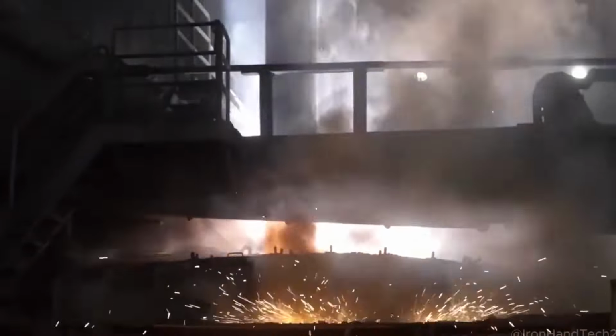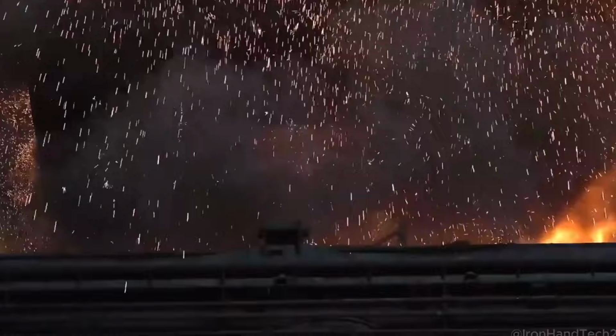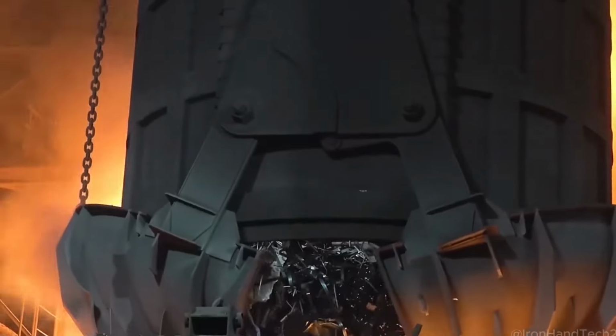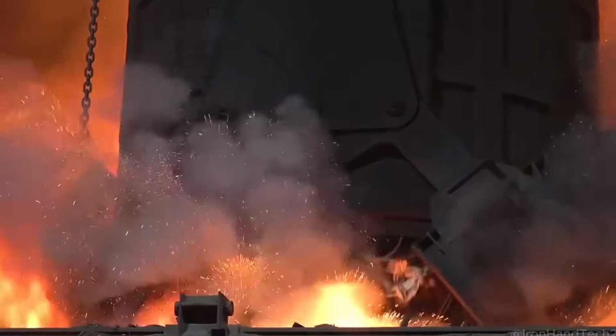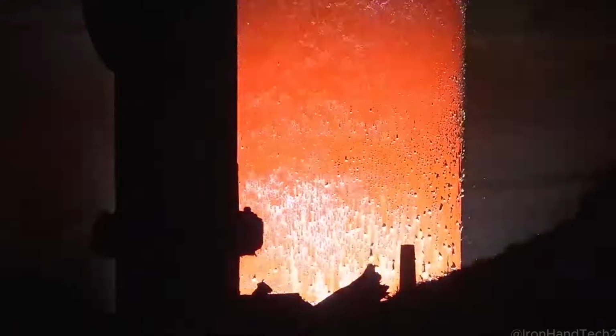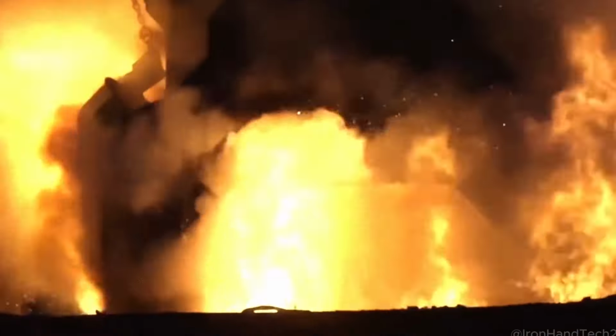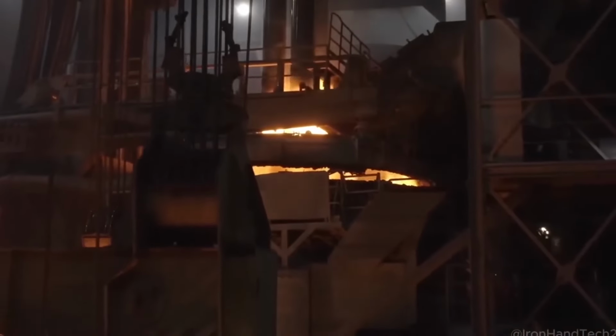This is where steel goes through its biggest transformation. Giant steel baskets, packed with shredded metal, are lifted high and tipped into electric arc furnaces, some of the hottest places on Earth. Unlike traditional blast furnaces, which burn iron ore and coal, electric arc furnaces run on electricity. This makes them far more energy efficient and environmentally friendly. Inside, carbon electrodes generate powerful electric arcs, heating the furnace to over 3,500 degrees Celsius, aka 6,332 degrees Fahrenheit, which is hotter than the surface of the sun. Within minutes, solid steel melts into a glowing white hot liquid, swirling like lava.